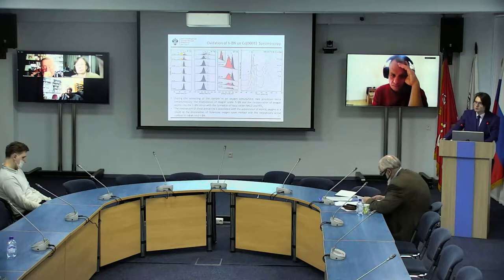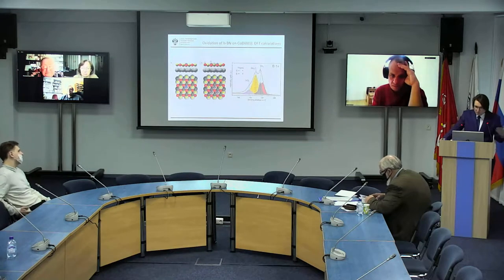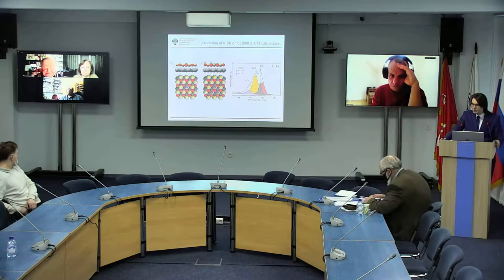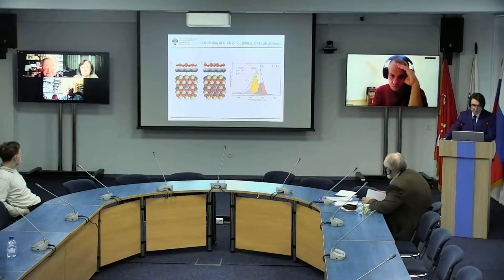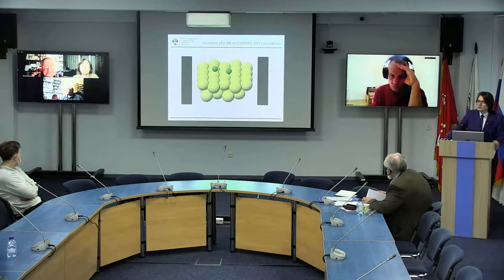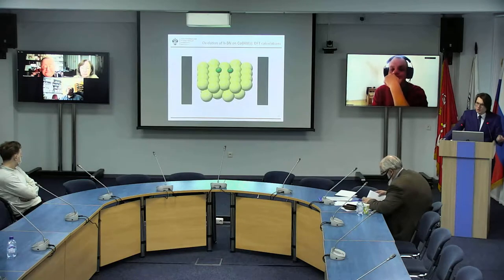The formation of these structures happened due to the introduction of oxygen atoms into the hBN lattice with a substitution of nitrogen atoms. In order to confirm this idea, we carried out DFT calculations, and we calculated the chemical shifts that corresponded with the experimental peaks. Here is the mechanism of this process. It is associated with the dissociation of molecular oxygen in contact with the catalytic surface of cobalt, with the formation of atomic oxygen that in turn is capable of oxidizing monolayers of boron nitride.